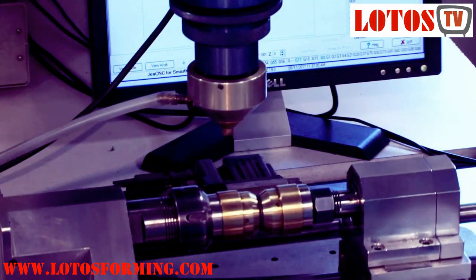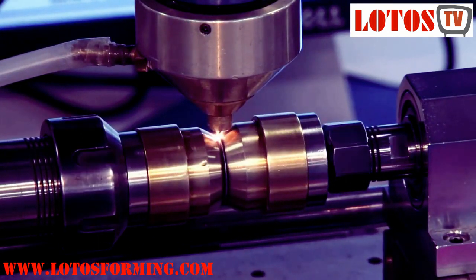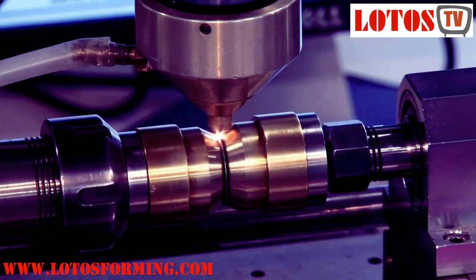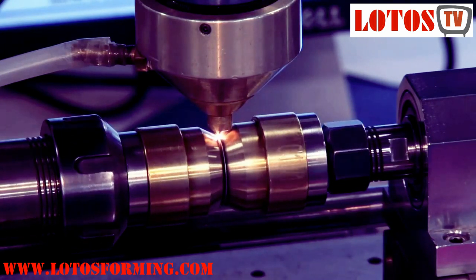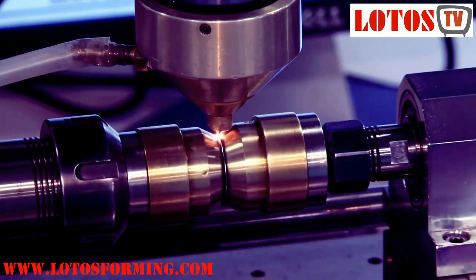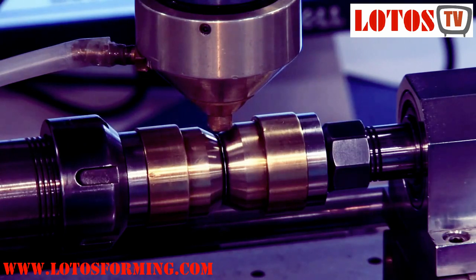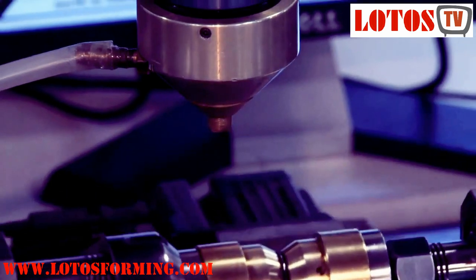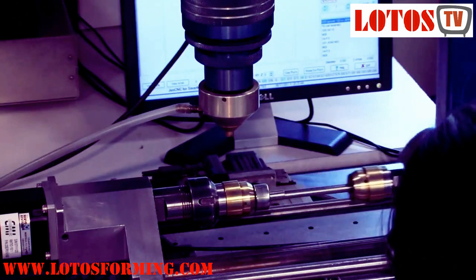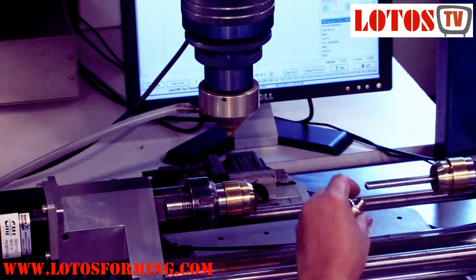In heat conduction welding, the materials to be joined are melted by absorption of the laser beam at the material surface. The solidified melt joins the materials. Welding penetration depths in this context typically are below 2 mm. The three main components in a laser system are the beam generator, the beam delivery system, and the focusing optics. The most common types of beam generators today are CO2, Nd.